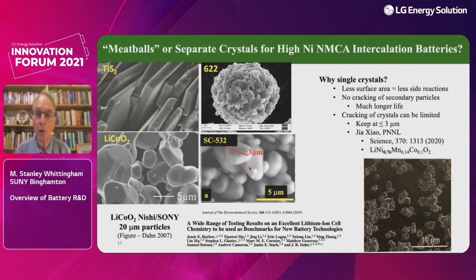And I think he's going to be talking about that in a moment, so I won't go into it. But there are two reasons for using single crystals. The same one Sony had: less surface area, less side reactions. No cracking of the secondary particles, which should give much longer life. And as Jia Xiao showed when she looked at single crystals of 76% nickel, published in Science last year, if you keep them at about 3 microns or less, the single crystals do not crack. So there is again a clear message.